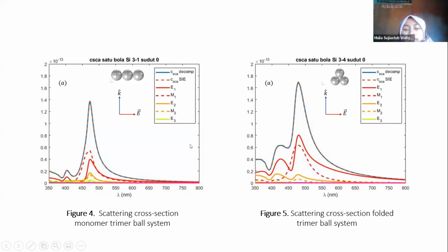Okay, first of all, the direction of the polarization that I use in this research: the electric field is in the horizontal direction, and the k vector means that the wave propagation is in the vertical direction. When we view from the multipole decomposition, the dipole field has a dominant contribution, the red line, in the monomer and folded trimer ball system.